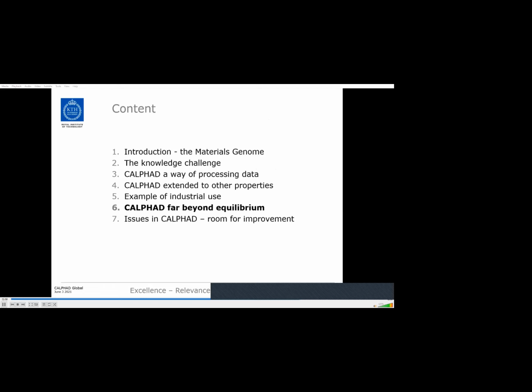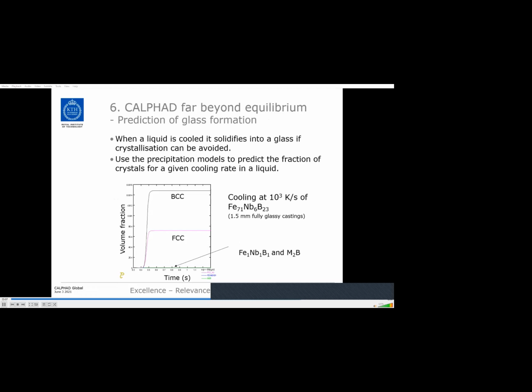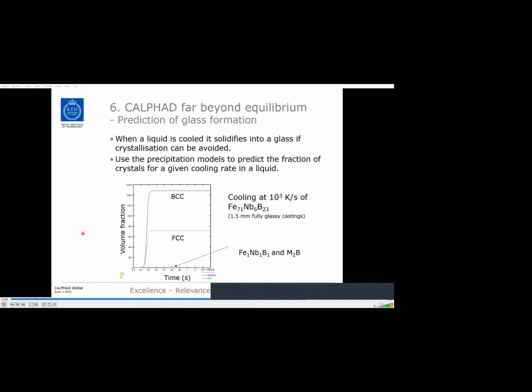So now let's look at the application of CALPHAD far beyond equilibrium. So here we look at the prediction of glass formation. It is known that when a liquid is cooled, it solidifies into glass if we can avoid crystallization. And that means that we can use the precipitation models to predict the fraction of crystals for a given cooling rate in a liquid. And here is one example where we see the volume fraction of the different solid phases, crystalline phases, when we cool a liquid of this ternary iron niobium boron alloy. And the cooling rate is here 1,000 degrees per second.